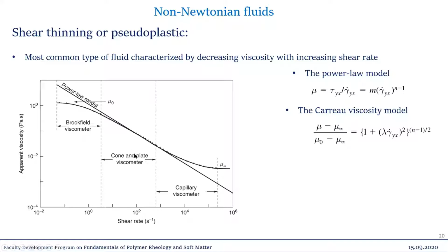So here we have compared this power law model and this Carreau model. You are able to see that the Carreau model fits both the low range data and the high range data, but the power law model is not able to predict this data. The symbols are the experimental data, right? So it is not able to cover this range, but in this range you can see that both models have almost similar fitting.